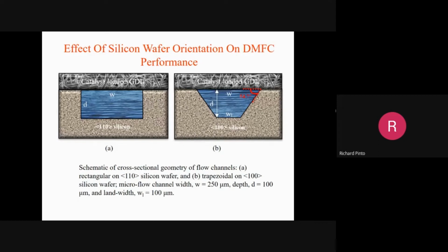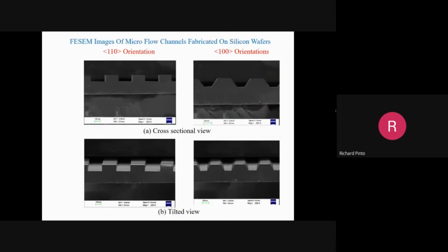It shows a schematic of the cross-sectional geometry of flow channels: a rectangular one using 110 silicon wafer, and B, a trapezoidal one on 100 silicon wafer. Microflow channel width is 250 micrometer, depth is 100 micrometer, and land width, in this case W1, is 100 micrometer. In the trapezoidal case, of course, the land width is the same as the total width, 250 micrometer. Okay, this is the schematic, and we'll see the actual picture in the next slide.